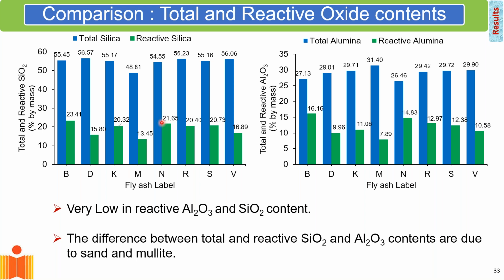And so when we did a little bit more analysis, we find that the difference here is because silica is also present in the form of quartz, and quartz is nothing but sand. So a lot of our fly ash tends to be loaded with sand, and when we are buying fly ash or using fly ash, we're actually paying for this silica, which is the blue bar, but we're only getting whatever is present in the green bar as the actionable or the material that is of use to us. So this is something that we really need to be concerned about.